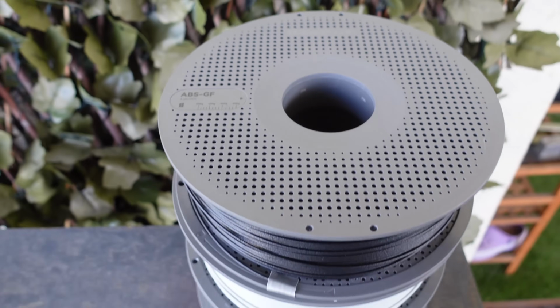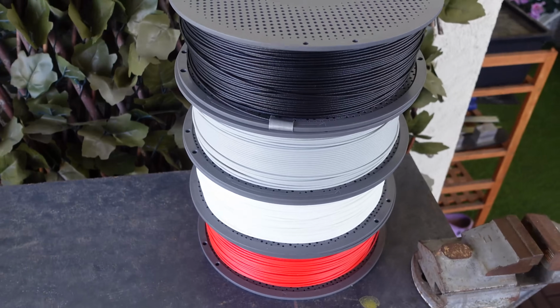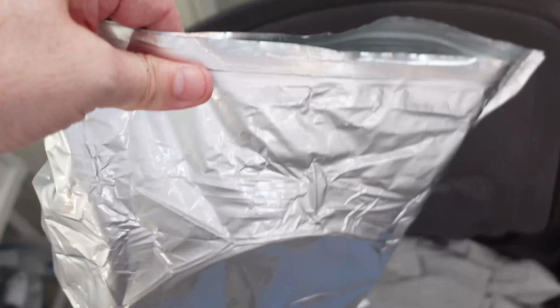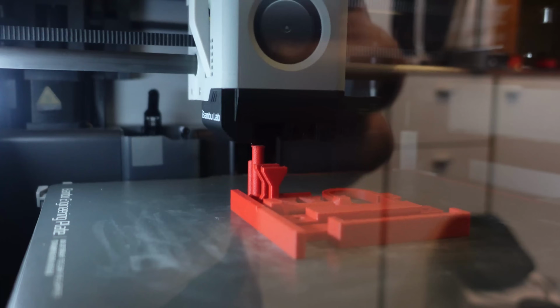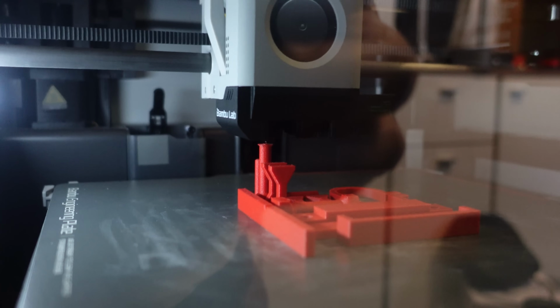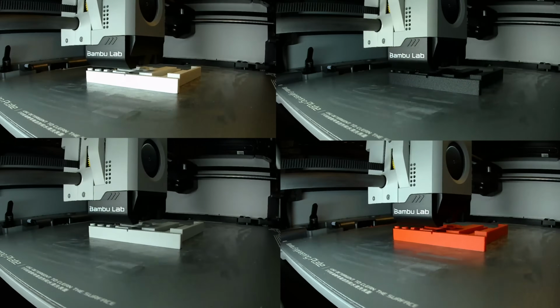About this glass fiber ABS. There is no significant difference in mechanical properties between the colors. Overall, it is good material, good layer adhesion, great resistance to bending and temperature. It is more brittle material compared to the regular ABS, and it is also more sensitive to moisture. So don't forget to store it in a dry place. The printing is easier with this material compared to the regular ABS. All my printings were successful on the first attempt.